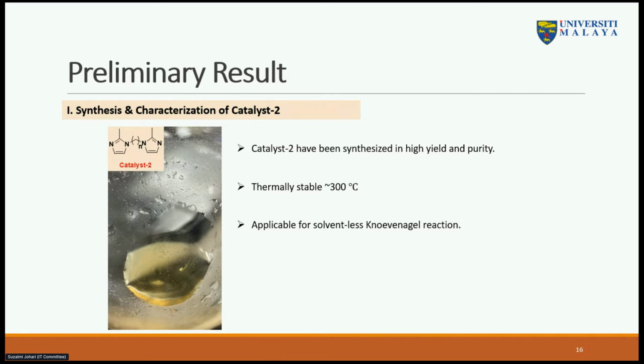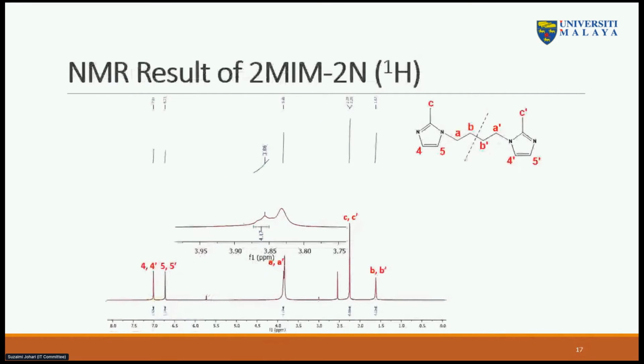And this kind of catalyst is applicable for the solventless Knoevenagel condensation reaction. And these are the NMR results to confirm the structure of catalyst 2. We can see here that because there is no CH2 at this C2 carbon, the 2 peaks here are attributed to the 4 and 5 hydrogens at the C4 and C5 carbons in the imidazole ring. The 1 and 2 peaks are attributed to the aliphatic side, and this very sharp, large, high peak is attributed to the hydrogens in the CH3 group.